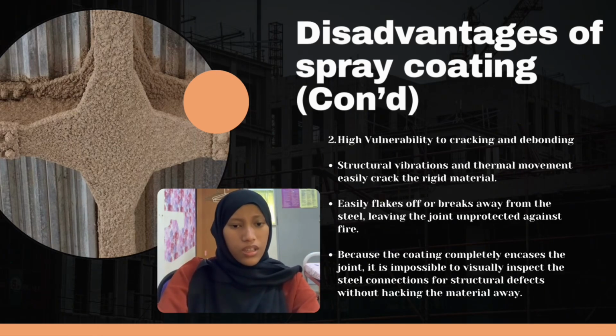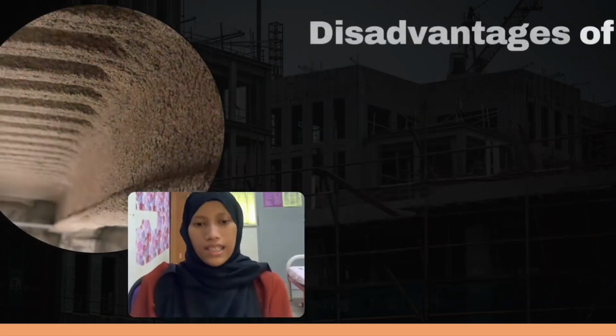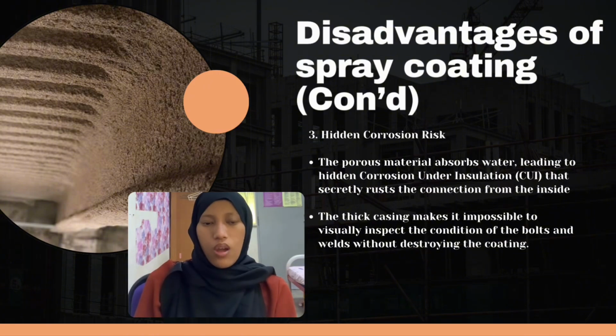To make matters worse, because this coating completely encases the joint, it becomes impossible to visually inspect the steel connections for structural defects without physically hacking the material away. This leads us directly to the third disadvantage, which is a hidden but serious threat, hidden corrosion risk, or what the industry calls CUI, corrosion under insulation. This is because cementitious spray is a porous material, it can absorb water, and when this moisture gets trapped, it leads to hidden corrosion that secretly rusts the steel connections from the inside out.